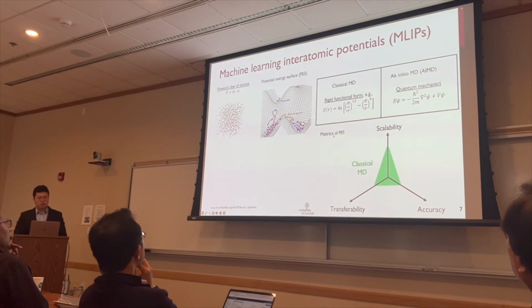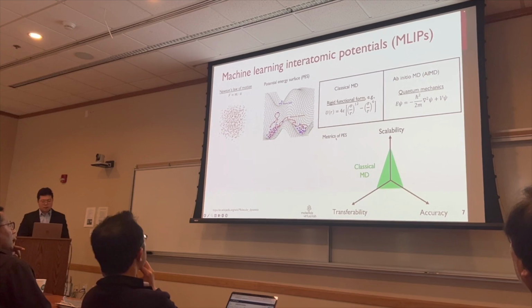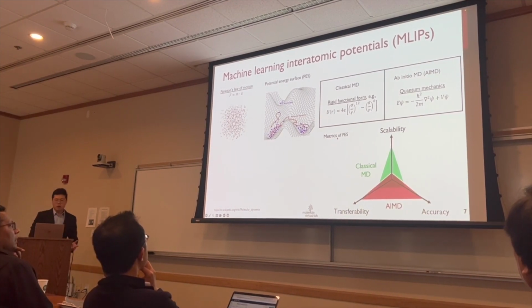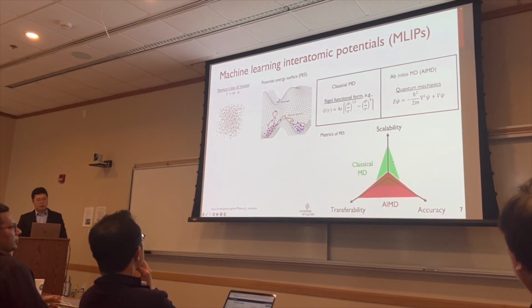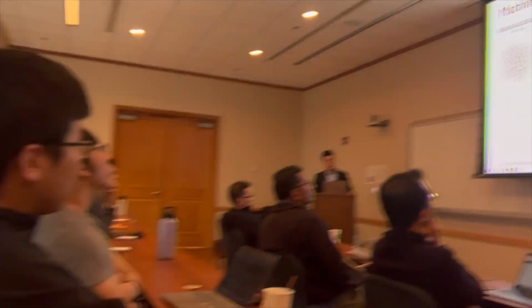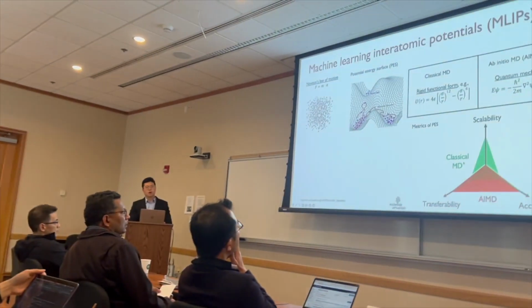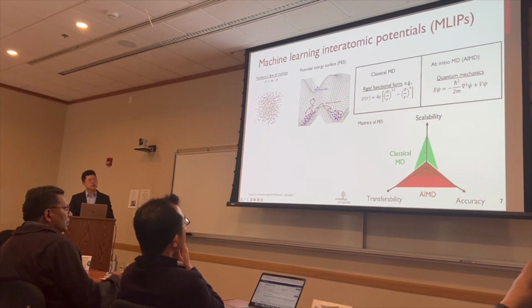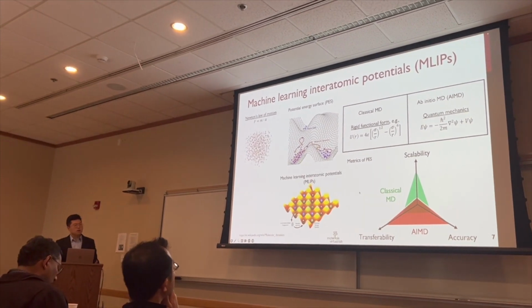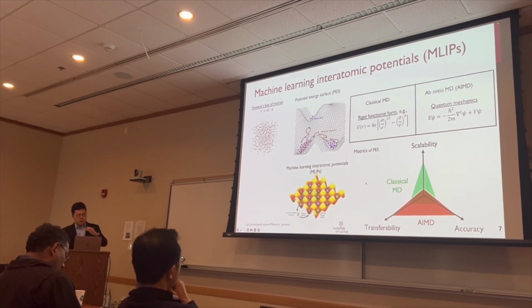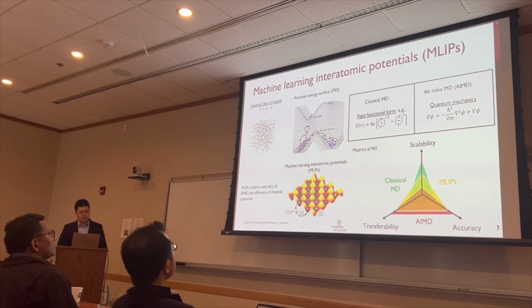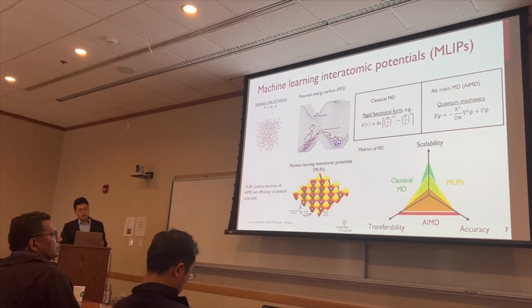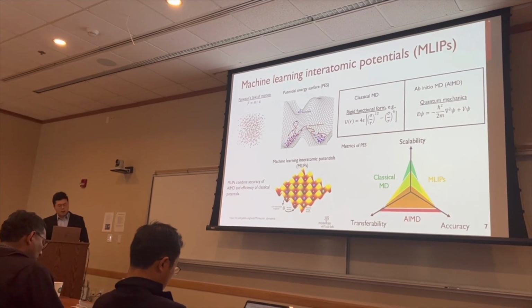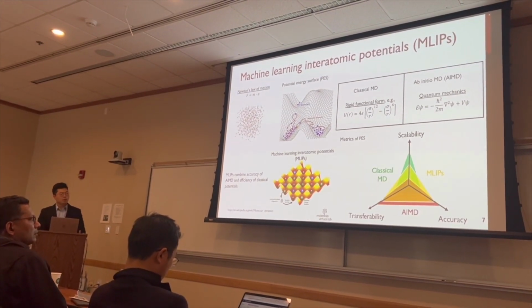While ab initio molecular dynamics, AIMD, is known to be highly transferable and accurate for the whole periodic table, its scalability is poor in that it's only applicable to below nanosecond scale simulation and at most hundreds of atoms. And in the recent 15 years, the machine learning interatomic potential has emerged as a tool that has been verified to combine the accuracy of AIMD and the efficiency of classical potentials.